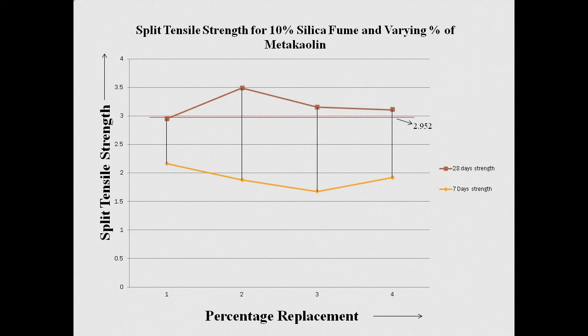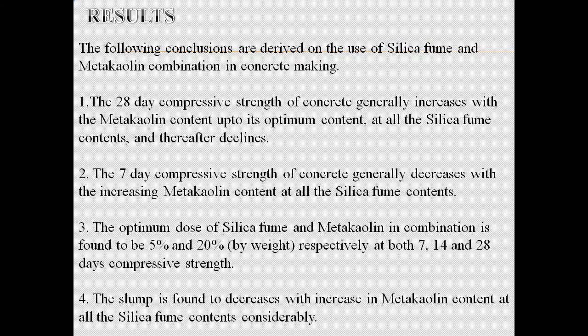Here is the split tensile strength for 10% silica fume and varying percentage of metakaolin, where the 28-day strength gives maximum results. The 28-day strength of concrete generally increases with the metakaolin content, but thereafter it declines when its optimum content is reached. The 7-day compressive strength of concrete generally decreases with the increase of metakaolin at all the silica fume contents. The 5-20 is the optimum dosage for silica fume and metakaolin for 7-day, 14-day, and 28-day compressive strength. The slump is found to decrease with increase in metakaolin content.